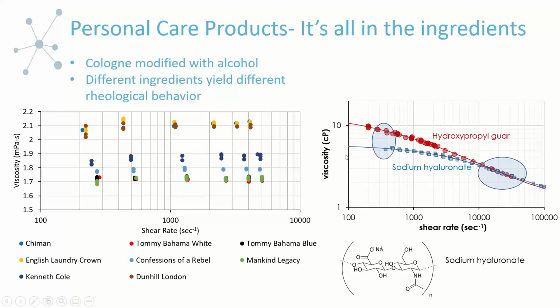So let's begin with the different colognes. Colognes are primarily modified with just changing the ratio of alcohol and the small molecules that give off the pleasant smell. And so as you can see, these are Newtonian fluids primarily, and that makes sense because all of the molecules within the formulation for a cologne are small in scale and don't undergo major changes when induced to flow under shear. And so these differences between this cohort up here and this cohort down here is primarily driven by the alcohol content. I believe this cohort primarily has about 83% alcohol by volume, and this cohort down here is closer to 80% or 81%.